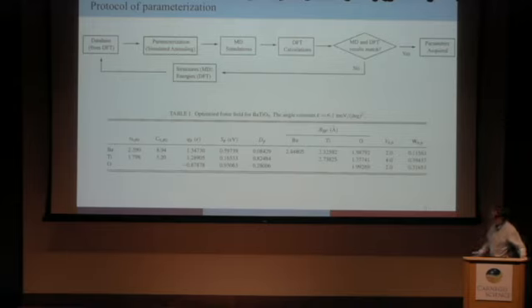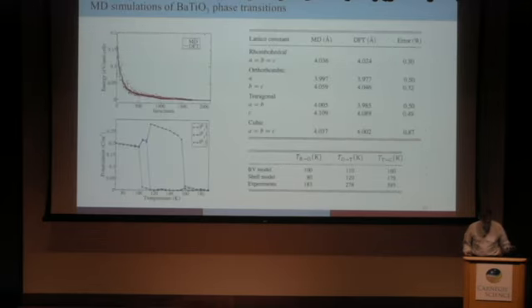And these are just the parameters that I mentioned to you, the prototypical bond lengths between the cations and oxygen, the charges, the short-range repulsion parameters, and so forth. Okay, and so as you can see here, the model is able to reproduce all the phase transitions, showing that you have equal polarization along X, Y, and Z at low temperature, and one of the components drops to 0, and a second one drops to 0, and then the last one drops to 0. So this would be the Curie temperature.